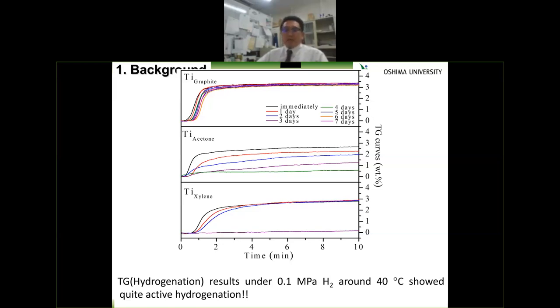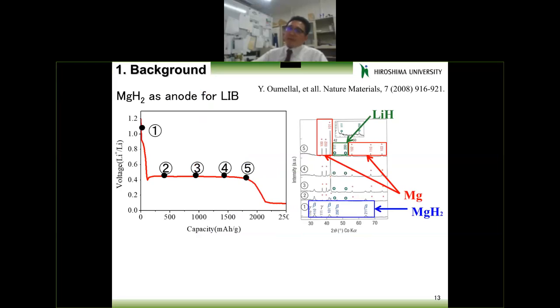And then by using this graphite and ball milling, the hydrogen absorption properties at room temperature can be kept for quite a long time. So that is quite an interesting result. So that is our activity on titanium and magnesium for hydrogen storage alloys. And then this is a totally different topic.